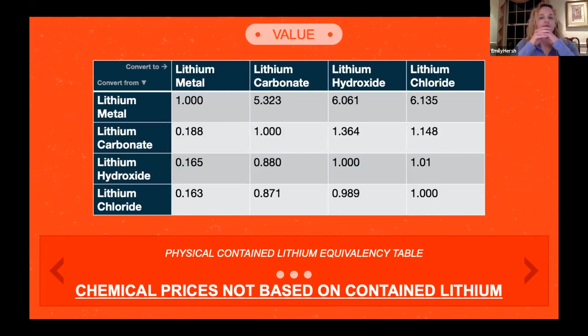This table takes a look at the concept of lithium carbonate equivalents. It shows you physically contained lithium within different materials, but this is to illustrate very clearly that the price of a lithium chemical doesn't depend on how much lithium it contains. A very easy one to look at is lithium carbonate versus lithium hydroxide. As you can see, there is more lithium metal contained in lithium carbonate than lithium hydroxide, whereas we're in a pricing situation currently where lithium hydroxide prices are in general much higher than lithium carbonate prices.